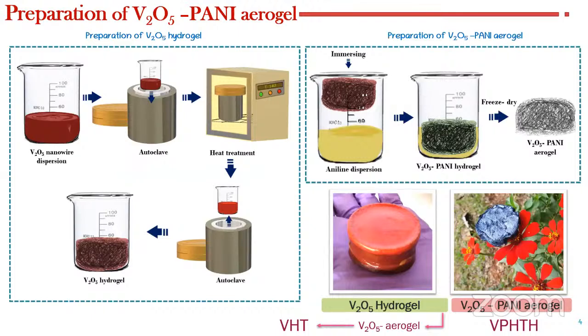Here we prepared a V2O5 PANI aerogel, which is a porous composite, through a simple hydrothermal route. We started with ammonium metavanadate and made a V2O5 nanowire dispersion. It was subjected to hydrothermal treatment for 24 hours at 140 degrees Celsius, and we got V2O5 hydrogel. This hydrogel was immersed in aniline dispersion to get V2O5 PANI hydrogel. It was freeze-dried to obtain V2O5 PANI aerogel. You can see the photographic image of the V2O5 PANI aerogel.